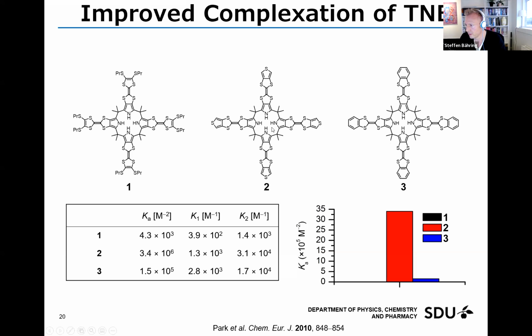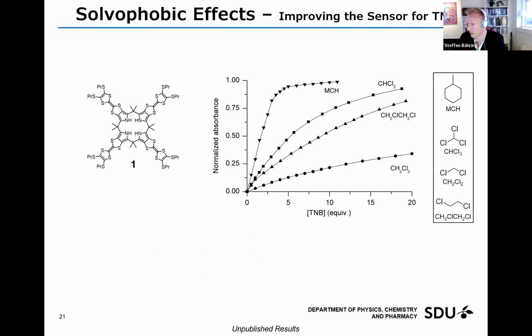Moving on, during my PhD, I investigated the effects of solvent because these compounds were originally thought of as only being soluble in chlorinated solvents. So not much has been done in experimenting with them. But you can see here that by changing solvents to a very soluble dichloromethane, we have a very low binding with TNB, and decreasing the solubility using dichloroethane, we increase the binding constant.